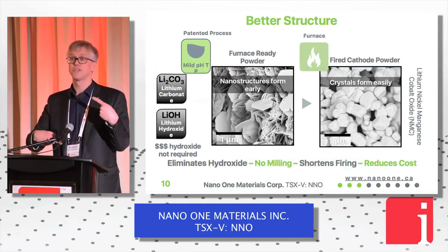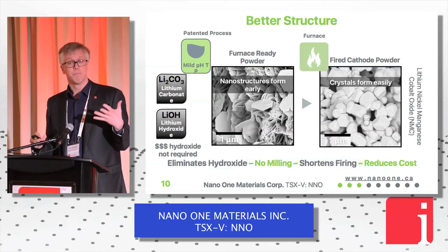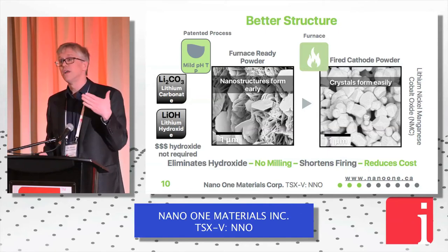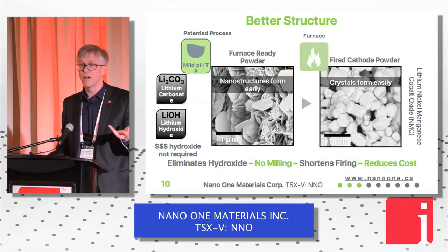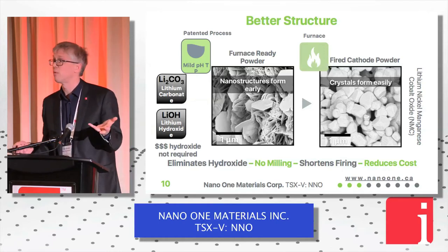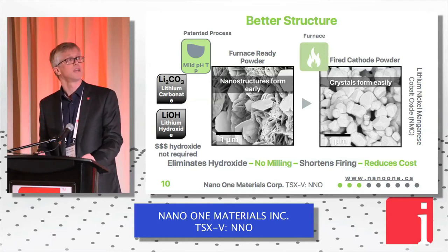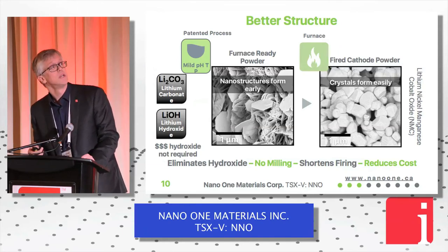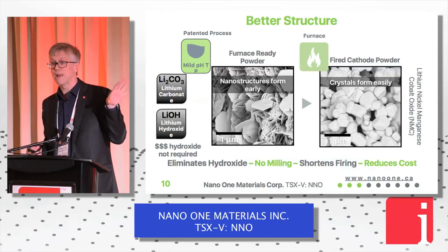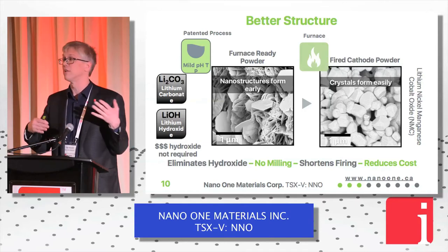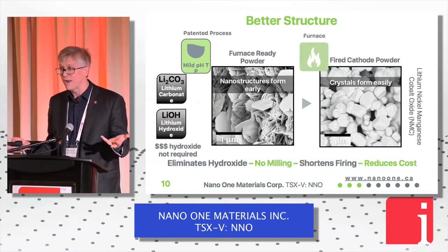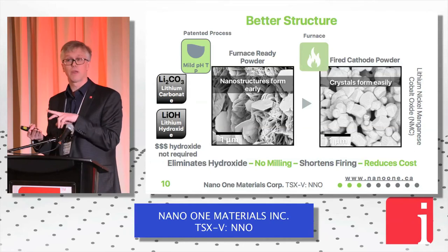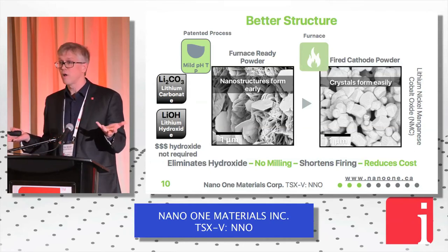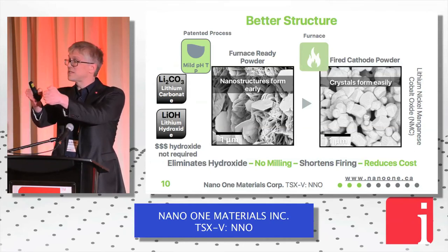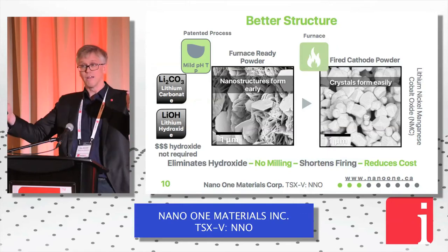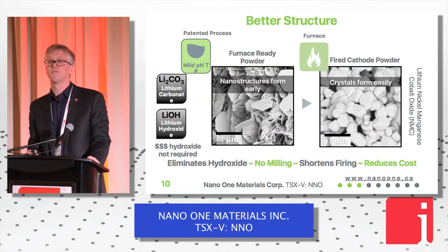So there's a chemical process that goes on in the furnace. But it doesn't take long. We've converted what takes days to fire in a furnace into hours simply because we're more effectively mixing those materials together. It also enables us to use lithium carbonate, because we don't care if it's lithium carbonate or lithium hydroxide, because we're going to dissolve it in water anyways. We don't care if it's ground or milled. We don't care what its crystallinity is. So we've all of a sudden taken this very narrow specification for battery grade lithium and widened it. And we believe that it will have tremendous value in the supply chain.